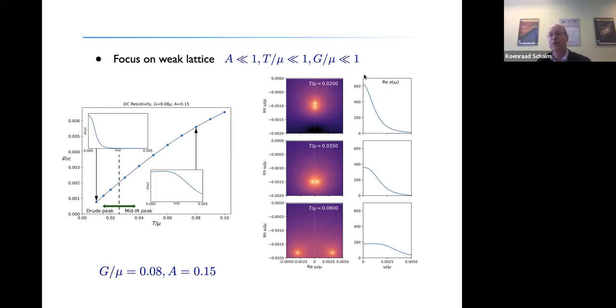So in the real part of the conductivity, it looks like you have a very beautiful single Drude-like peak that dominates the low frequency and specifically the DC transport in the system. But as you increase the temperature, these 2 poles can now collide, right? And then they can move off the real axis. And that is the mechanism by which this happens. So the Drude pole collides with the charge diffusion pole. They can become propagating. And now you can have a mid-IR peak, right? All of a sudden off the zero frequency axis.